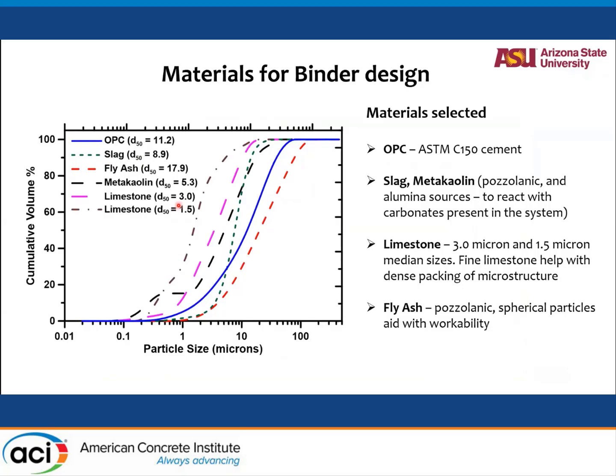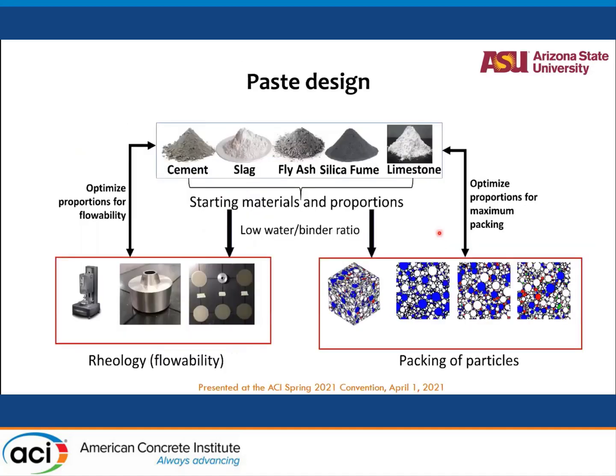Slag and metakaolin, and fly ash also, are helpful to pack the particles as well as to give you additional reactivity. Limestone helps with dense packing of the microstructure, and if you have enough amount of aluminates in the system, for example, like slag or metakaolin, you can have carbonate synergy with that, and you can form carboaluminates, which also will give you more packing and increased properties. And limestone is used because it gives you a better workability, it helps you fill the particles better. And so all our mixes that we have use limestone.